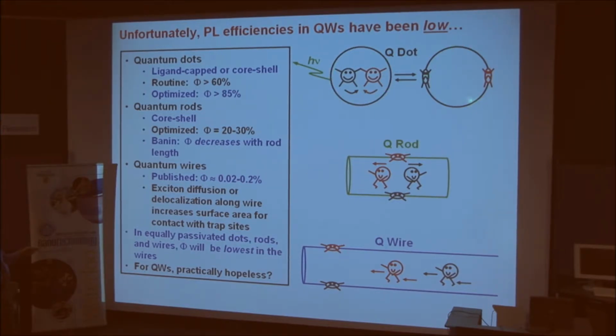But if there are trap sites on the surface of the dot, then the electron and hole can become trapped on the surface, localized, where their wave functions no longer overlap. And here the probability of radiative recombination is low. And so PL efficiency is a measure of how well the surface is passivated. A high PL efficiency tells you that trap sites at the surface of the nanostructure have been minimized.